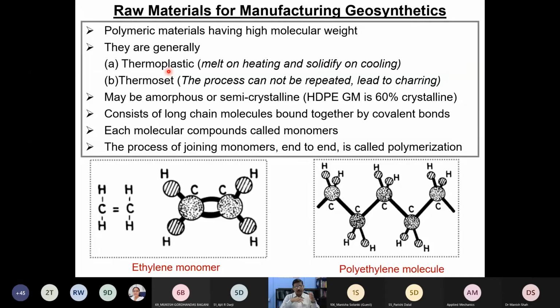The diffusion of any organic compound through a polymer predominantly happens through the amorphous regions of the geomembrane, not through the crystalline regions. So if the polymer becomes more crystalline due to aging or due to the manufacturing process itself, it is really good from the diffusion point of view. But if the crystallinity increases too much, you may end up breaking the polymer due to stress cracking. The entire polymer can become something like a biscuit. You can simply break it like this. We don't want to see that kind of scenario, so we need to focus on how the crystallinity is going to change.